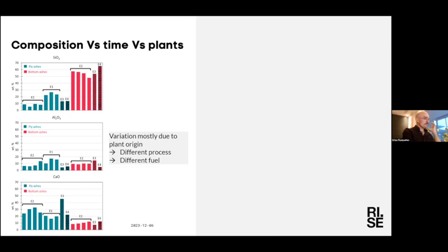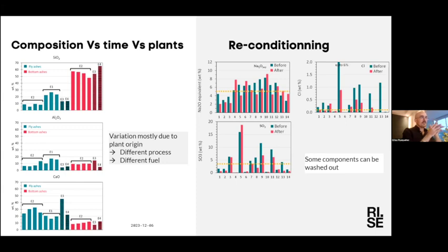Of course, we have all other components that we don't want to have, such as alkalis, chloride, or sulfate. So you need to recondition the ashes. We did that with some washing, and we studied the different parameters, such as the liquid to solid ratio, the time of the leaching process, how many times you need to do it. And the results for some samples are here. So before in blue and after the reconditioning in red.